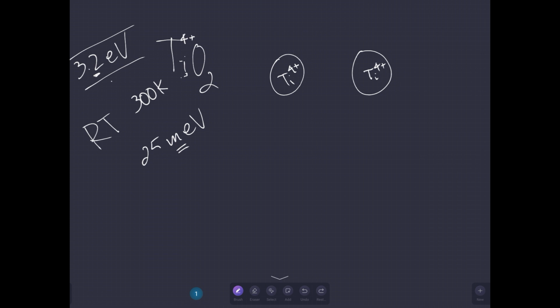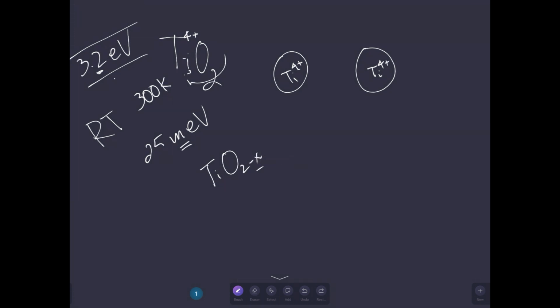So that's not possible. But if you introduce a point defect in that material, you'll see it becomes possible. For example, if you create a non-stoichiometric oxide, titanium O(2-X), non-stoichiometric - you can see that for each titanium, there are less than 2 oxygens. X is something you can actually tune using this so-called controlled atmosphere furnace processing - that's how controlled atmosphere processing comes in, you can tune that X.